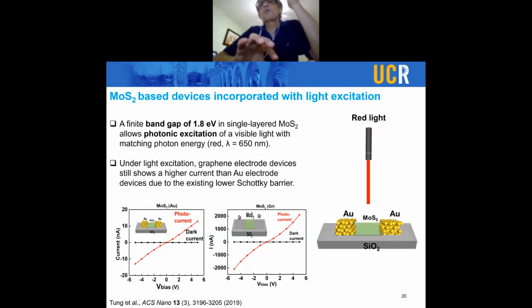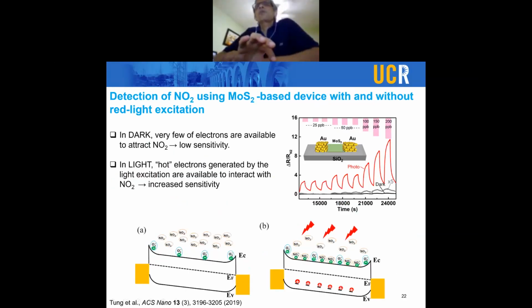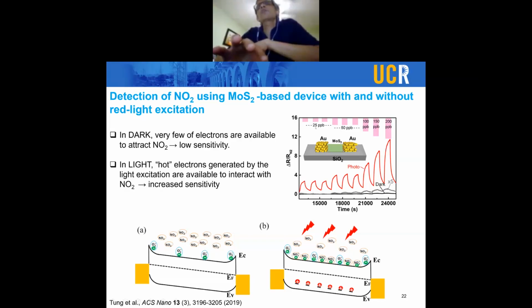So having achieved some of the goals of lowering the Schottky barrier and doing optical gating, we decided to apply this particular platform for detection of NO2, as opposed to toluene, because working with toluene was not that easy for us, because generating different concentration vapors is tedious. So we decided to look at the MoS2 for NO2 sensing. It has been reported it's a good sensing element for nitrogen dioxide gas. And here's a comparison for the gold electrode, not the graphene electrode, with the MoS2 channel, with and without light for different concentrations of nitrogen dioxide: 25 parts per billion, 50, 100, 150, and 200. You do see a concentration dependent response and a very significantly amplified response over the dark current.